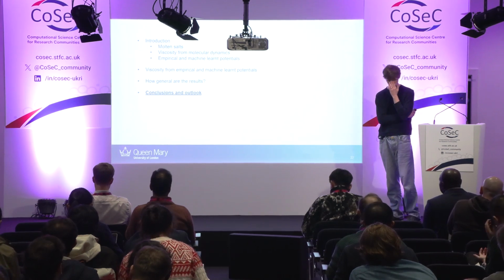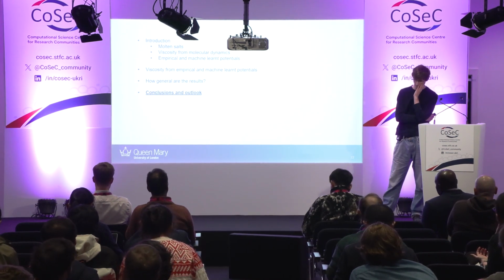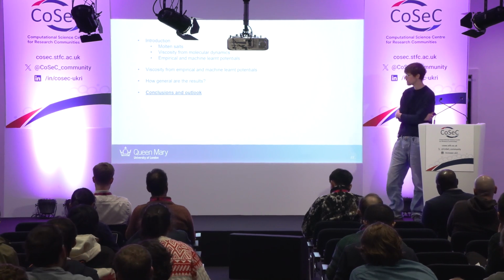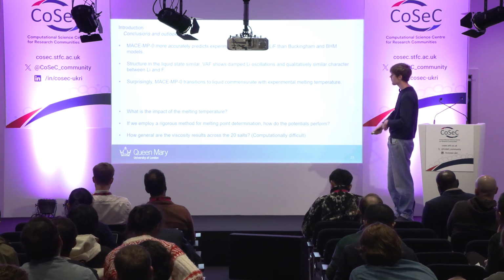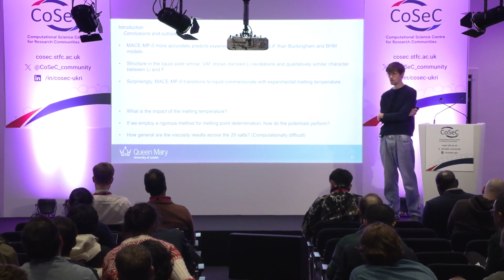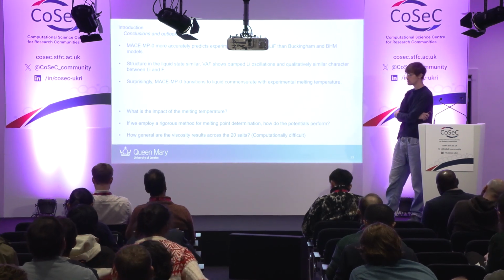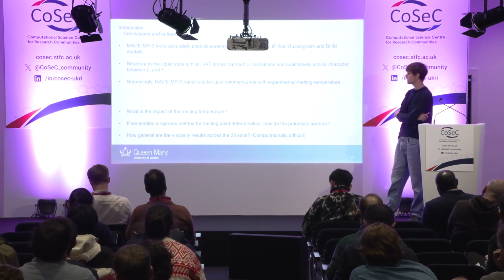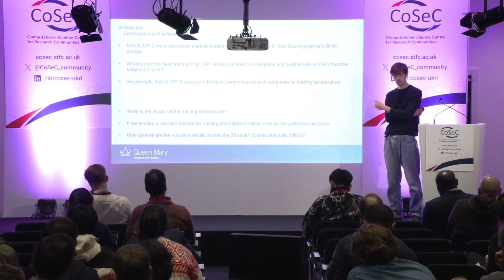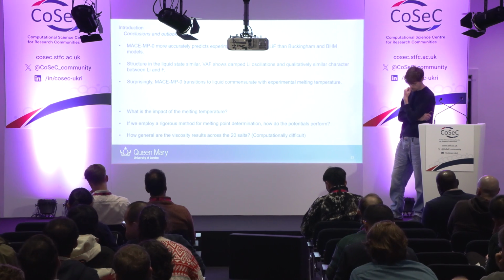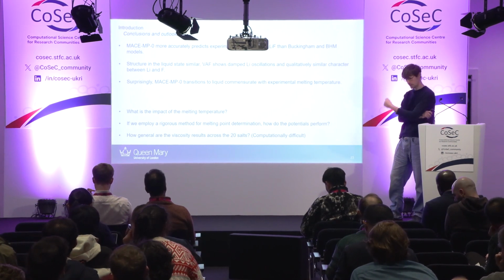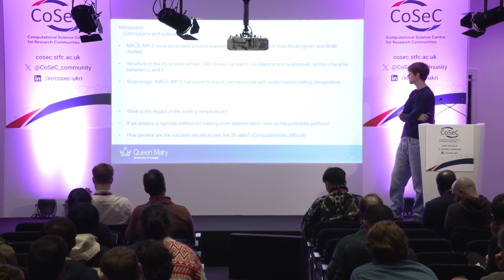So with that, I'll move on to the conclusions and outlook of what we're going to look at in future. What we find is the MACE model is generally quite useful, quite accurate at predicting viscosity, at least in lithium fluoride from what we've currently looked at. And we see a similar structure but slightly different dynamics. And surprisingly, the MACE model hits that instability at roughly the experimental melting temperature.